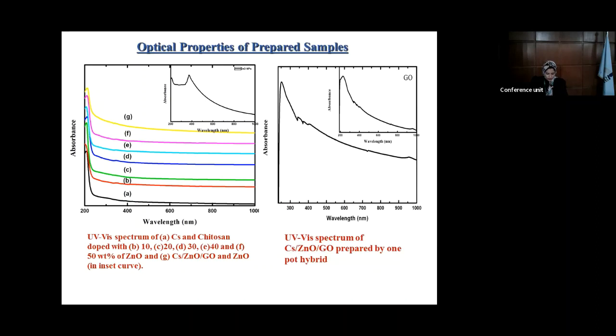The presence of delocalization along the polymer chain has been stated to be due to the strong changes toward the longer wavelength. And there is a weak band at 315 nanometers that increases with increasing the filler, which indicated the miscibility and the interaction between chitosan and both zinc oxide and the graphene oxide. In the one-pot hybrid, there is an absorption peak at 252 nanometers attributed to the interaction between chitosan and graphene oxide, zinc oxide.